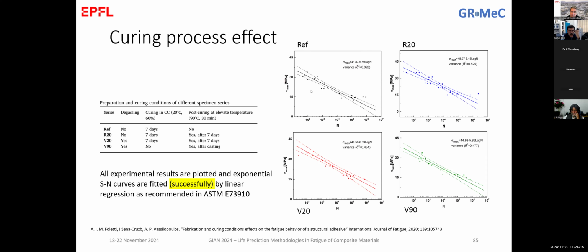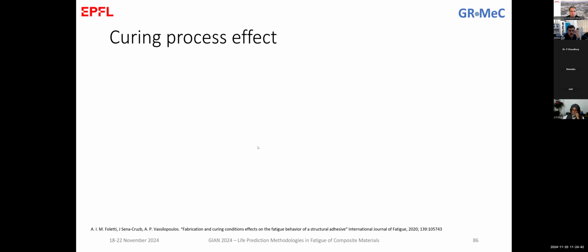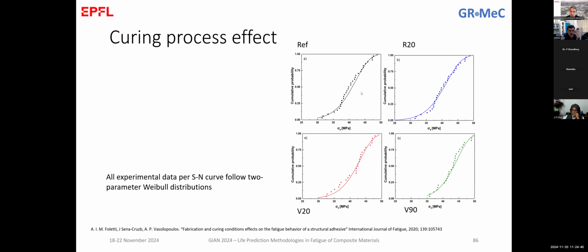A very interesting result here is that fatigue results can again be fitted by these typical SN curves that are defined by ASTM. Here you see the linear fitting, linear regression recommended by ASTM E739. So again, we validate that we can use these fitting methods for these materials.